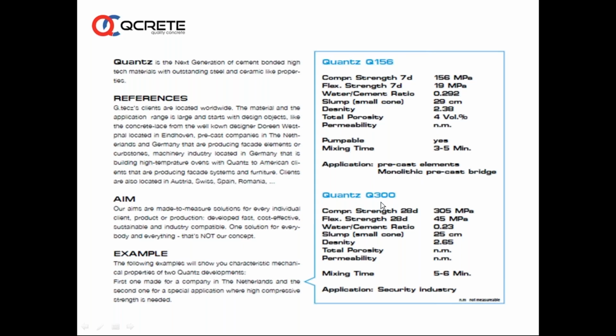The next is astonishing. It is 305 MPa, compressive strength at 28 days. Flexural strength. You can see all these flexural strengths are significantly improved. The flexural strengths are very high when compared to normal concrete. You can see here the flexural strength is 45 MPa. Water cement ratio is 0.23. Porosity not measurable, permeability not measurable. Okay, mixing time is 5 to 6 minutes.